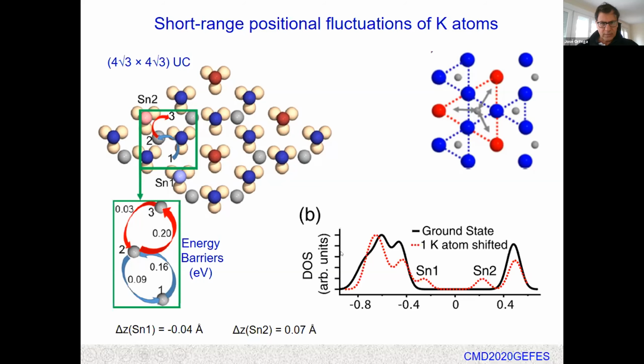Here we have the density of states for the ground state, the black line. This is the gap, the HOMO-LUMO gap. And the density of states where one potassium atom has been shifted from the original position in the ground state to this new position. So there is this jump of the potassium atom from position 1 to position 2. And this gives rise to two new states, dangling bonds. The tin 1 atom, which was originally in the ground state a fully occupied dangling bond, has now moved into the gap. And this other state corresponds to this other tin atom, which initially was an empty dangling bond, but now, due to the presence of the potassium atom nearby, also moves into the gap. So this is empty, so the gap is now reduced.